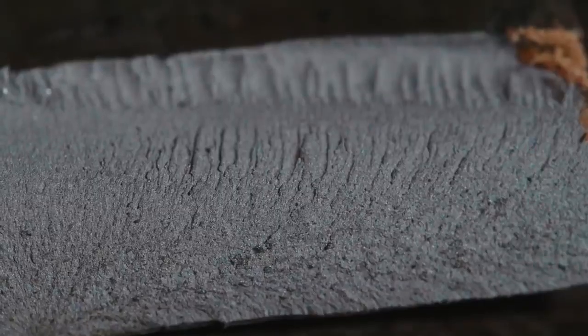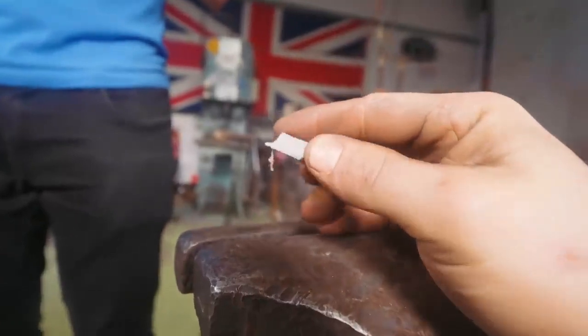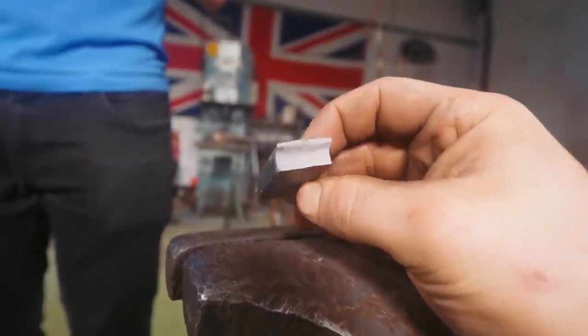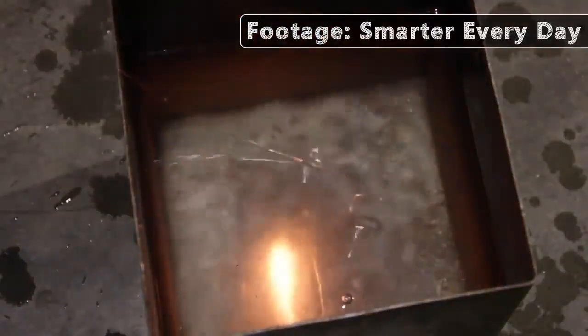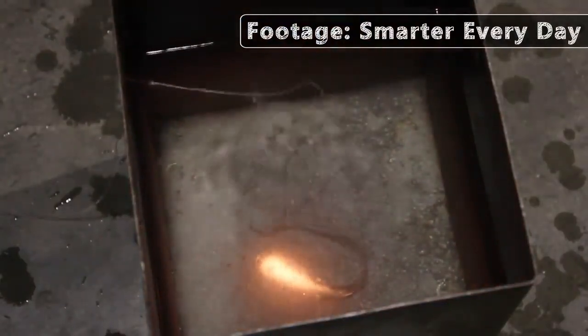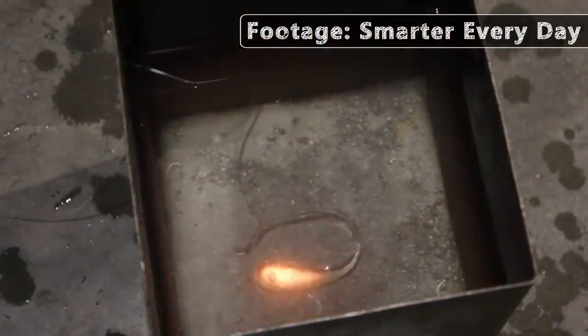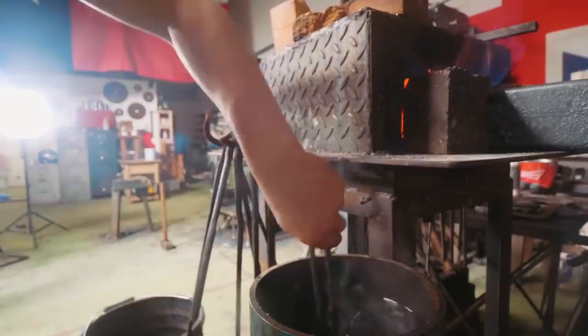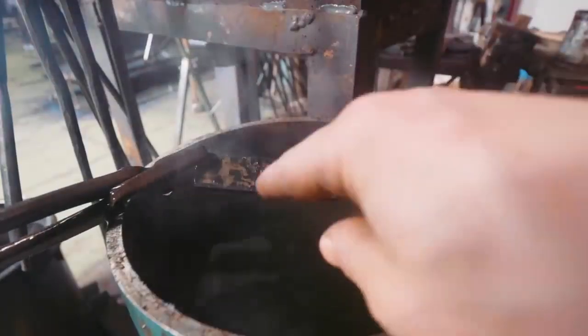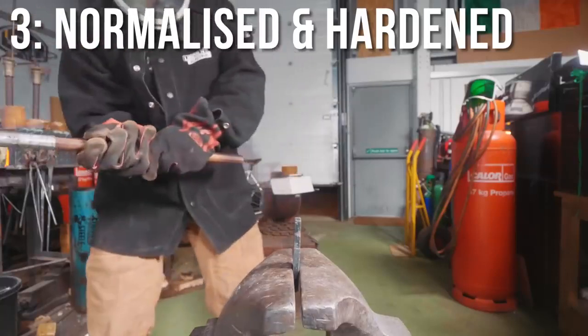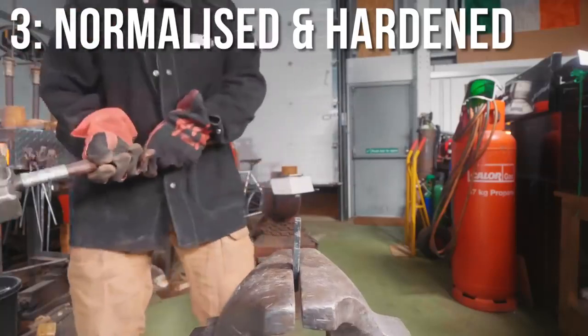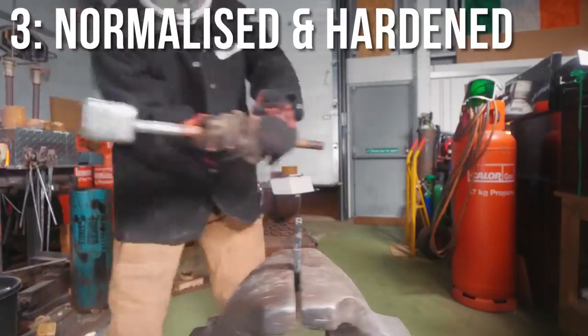This crystal structure has a huge amount of internal stretching, in part because the carbon trapped within the crystal structure causes the crystal lattice to deform, but also because during the rapid cooling, the surface cooled much faster than the internal material. This causes internal tension in the material. These internal strains make it harder for additional deformation to occur, but this does not make the material stronger. It simply means that it will not stretch and bend before breaking. And when it finally does fracture, all of this internal tension is suddenly released in an explosive expansion.